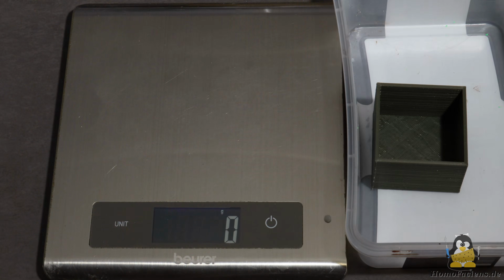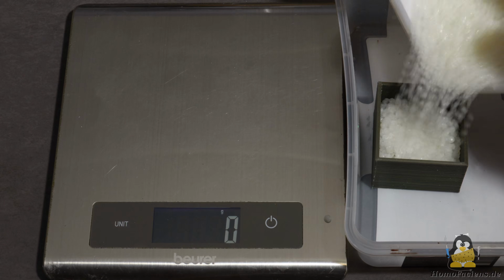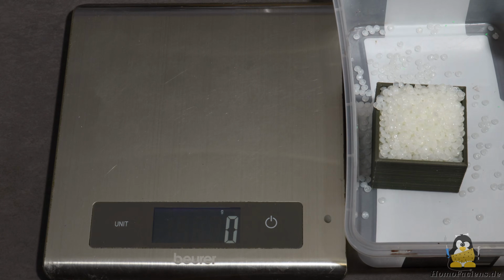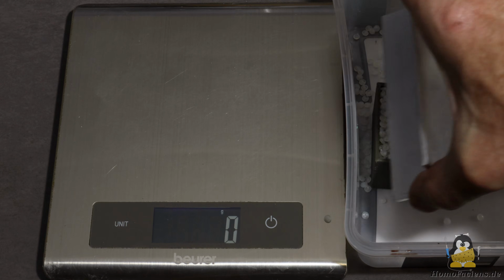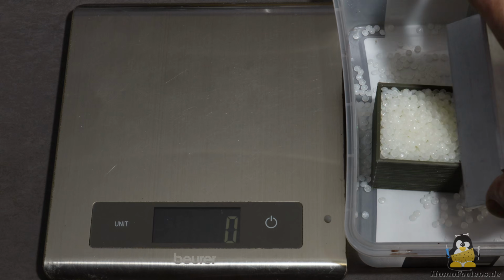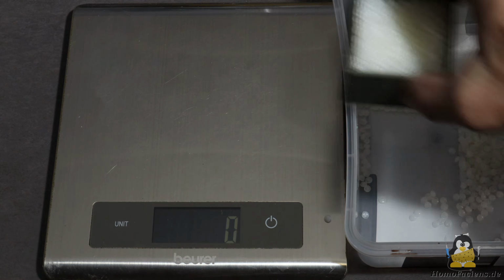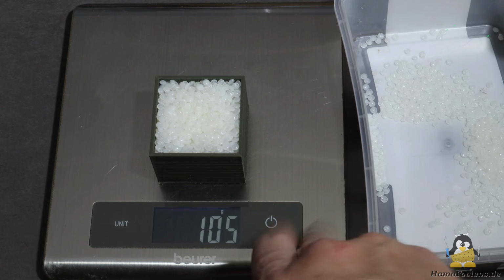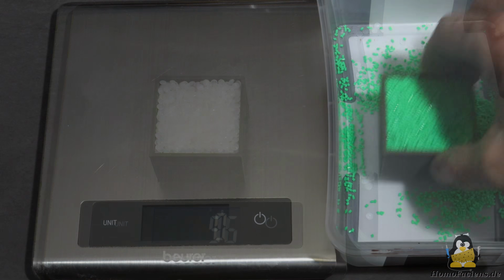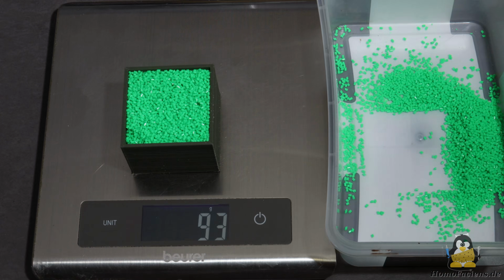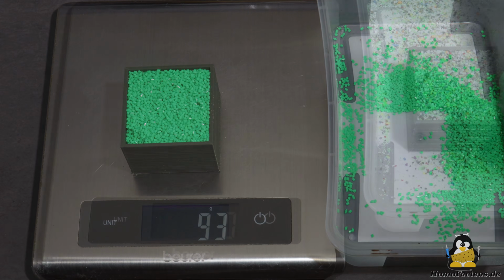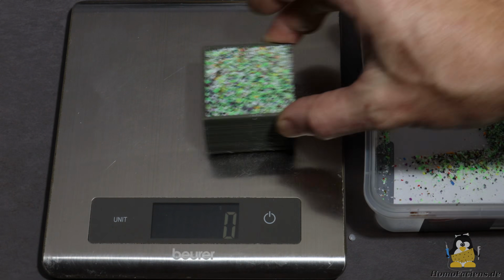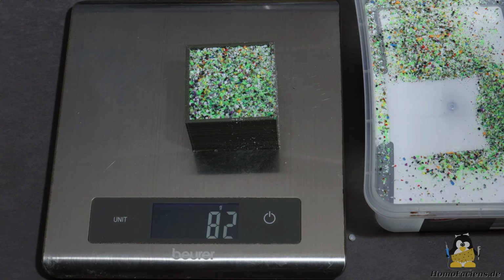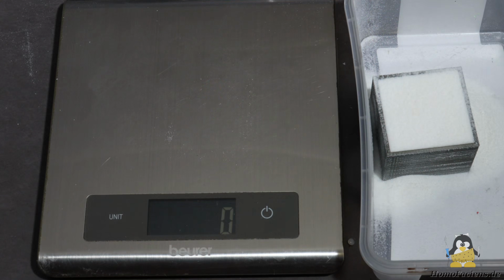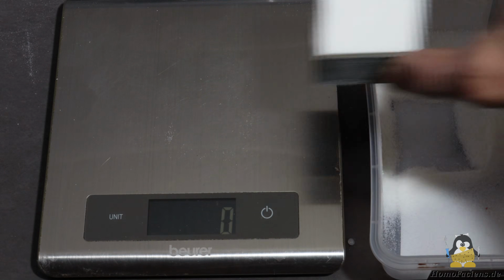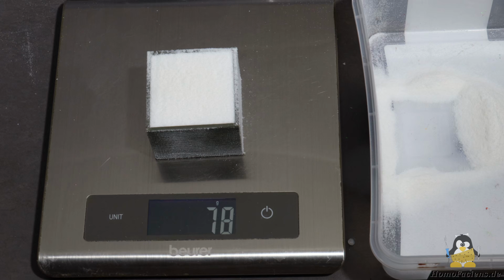The raw material consists of solid plastic particles with air gaps between them, so what are the densities of the materials shown here? 100 cubic centimeters of granules weighed 105 grams, corresponding to an average density of 1.05 grams per cubic centimeter. For pellets it is 0.93 grams per cubic centimeter. For the recycled powder we get 0.82 grams per cubic centimeter. And finally for the industrial powder it is 0.78 grams per cubic centimeter.